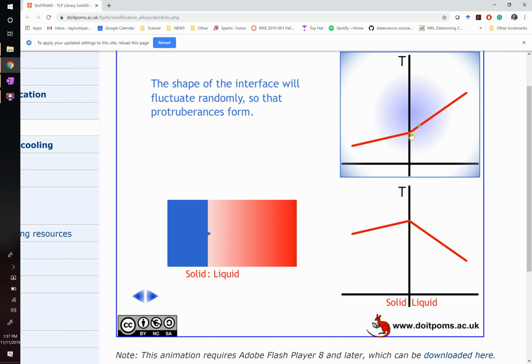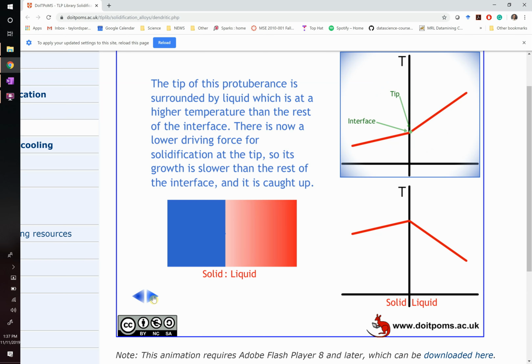But think what that's doing. In terms of temperature, as it extends out into the liquid, it's going up in temperature. So that little protuberance, as they're calling it, is going to melt again because it's moving into a region that's hotter. So even though it forms momentarily, it's going to disappear because it just melts again. In other words, this whole thing's going to grow nice and uniformly. That leads to the columnar growth that you saw, right?